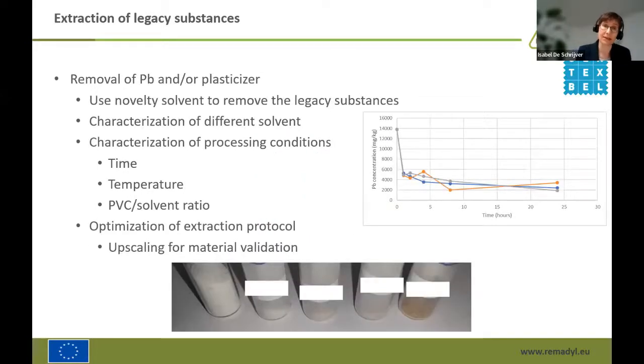The next step is, instead of only removing plasticizer, also trying to remove the lead out of the PVC materials. And there, supercritical CO2 is, of course, one aspect, but it's not sufficient. So there we are looking at novel solvents, which are also green solvents, safe solvents to work with, working with different ratios of solvents. And again, we did a lot of optimization: time, temperature, combination of a certain ratio of PVC with some solvents. And you see here some pictures at the bottom of the PVC samples that were being processed, and you see some of them are still quite nicely white. The right one has a brownish color because there we had some degradation due to the solvent choices we made.